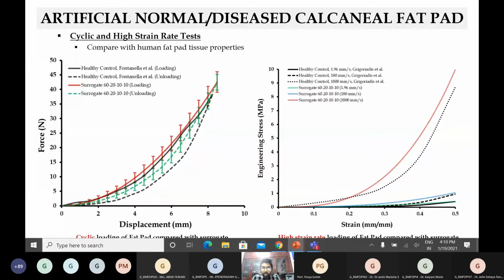Sorry about that. The second part is we are looking at specific high strain rates as well, going from 1.96 to 1800 millimeters per second, and we looked at how the properties compare here. The cyclic strain rate properties were pretty good. The surrogate properties for the different strain rates came out to be okay, not that good. As we can see, the black dotted lines compared to this one are not that close, but there is some correlation, like at least this one is not going up or down. Okay.